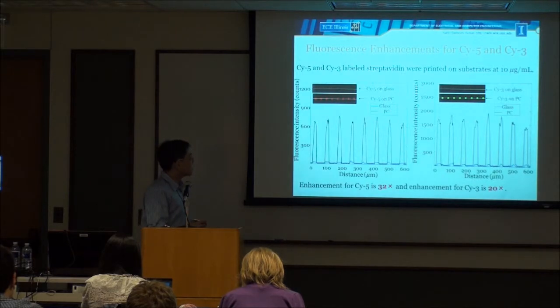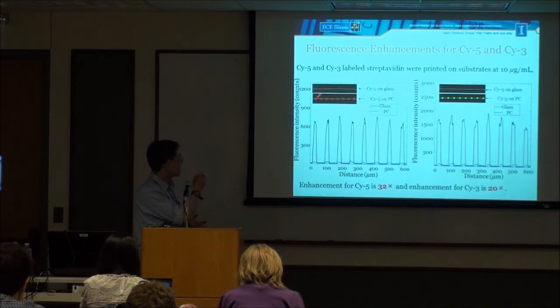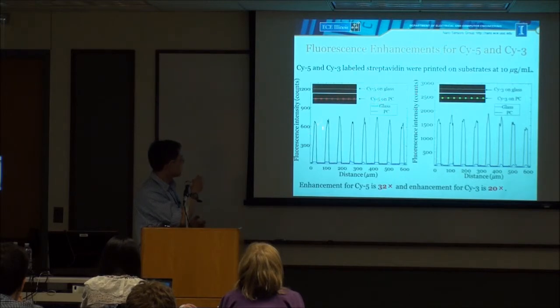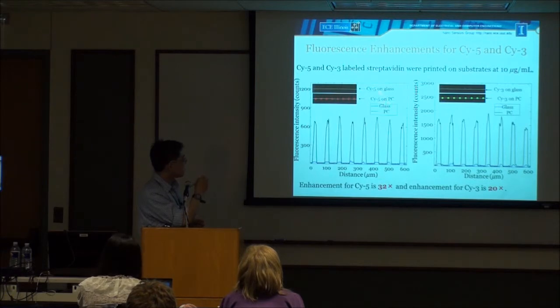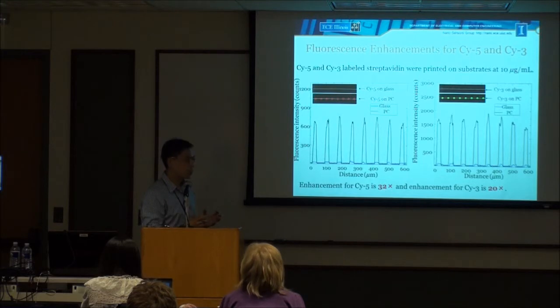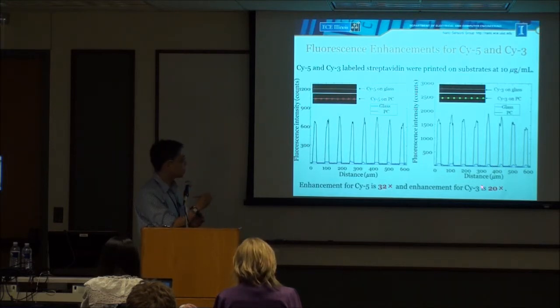So we did a simple experiment to show the simultaneous fluorescence enhancement on the substrate. The left figure shows the enhancement from Cy5 molecules on photonic crystal. The black curve is the emission intensity profile taken from this cross section. If you compare the photonic crystal and glass, our photonic crystal provides 32 times enhancement compared to glass. Simultaneously, you can get enhancement from Cy3 dye, which is a little bit lower because of the difference in the distribution of the resonance mode. I still get about 20 times enhancement from the Cy3 molecule.